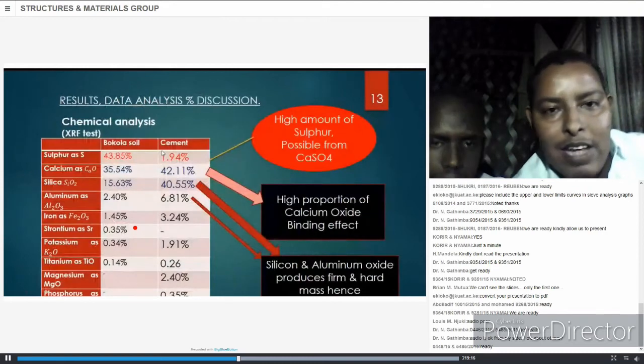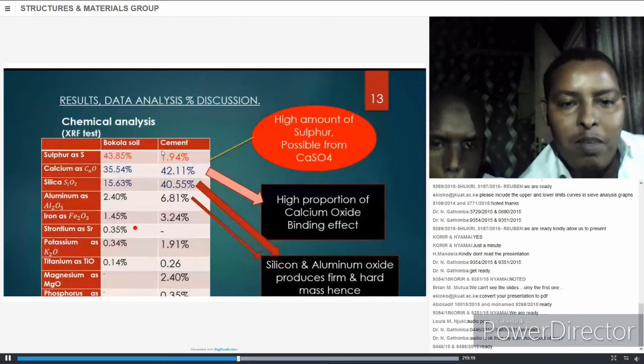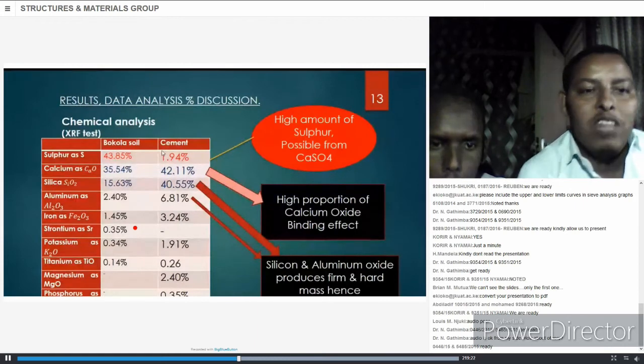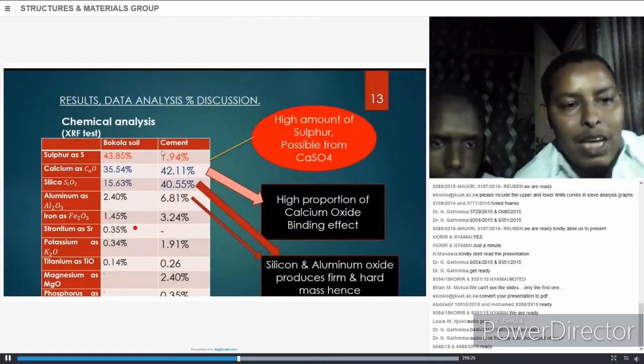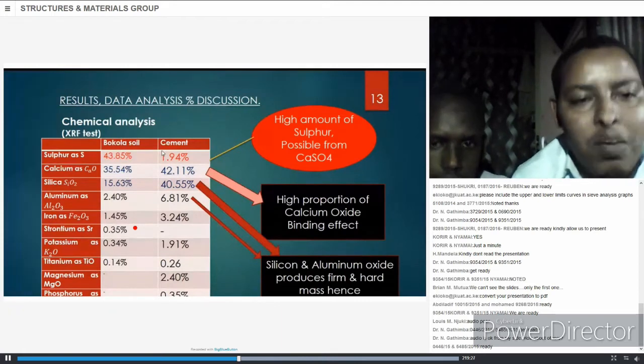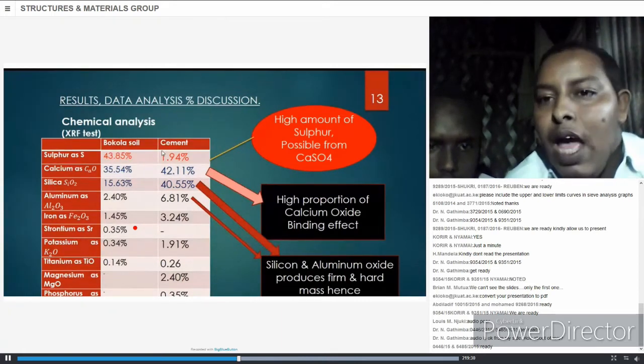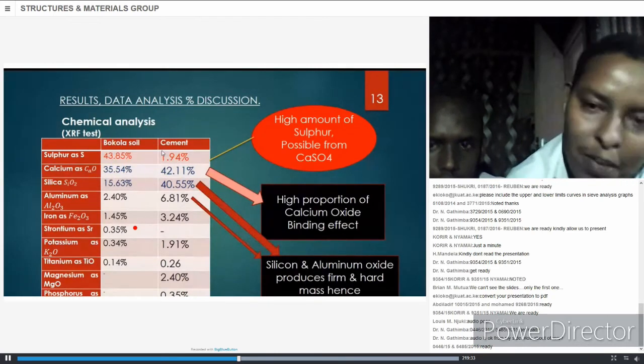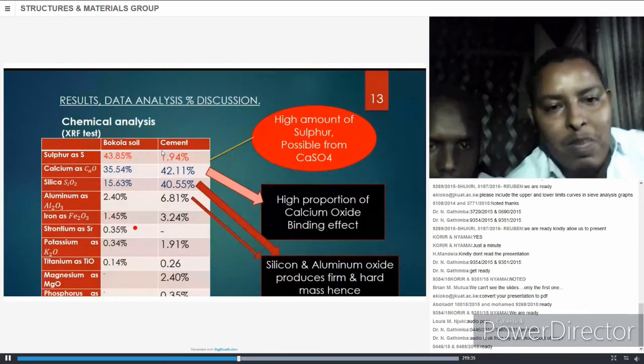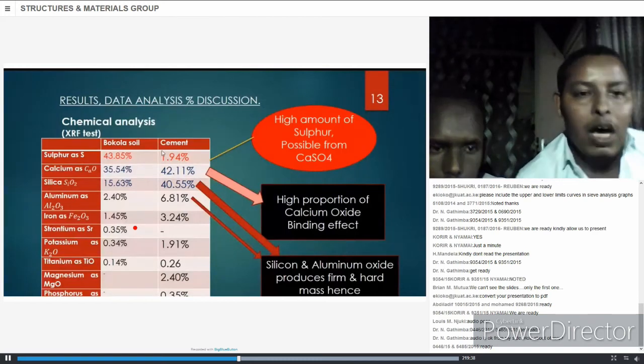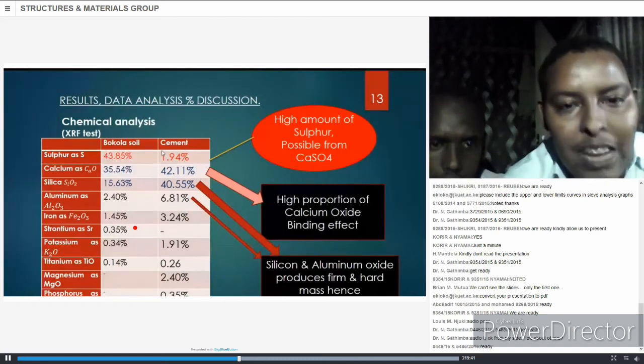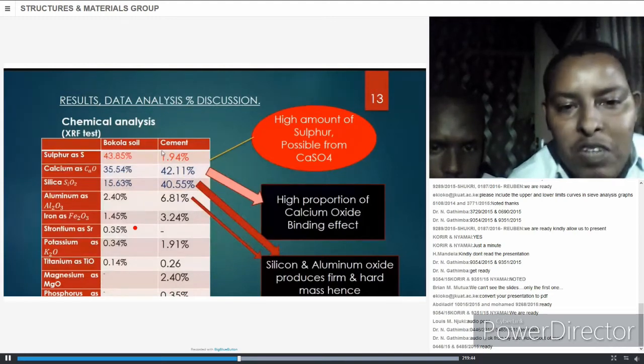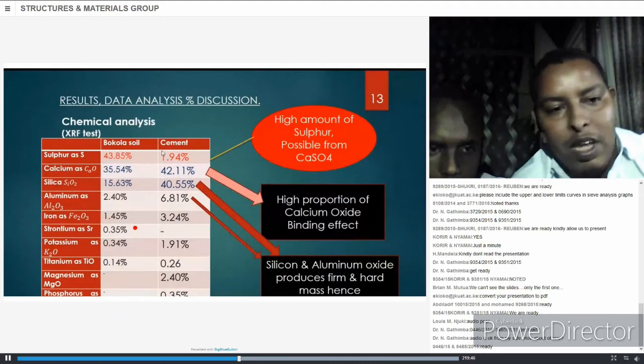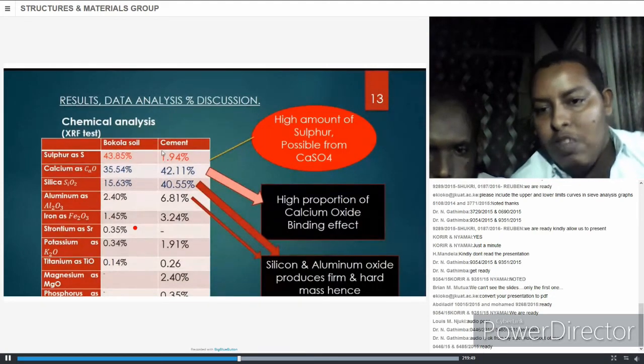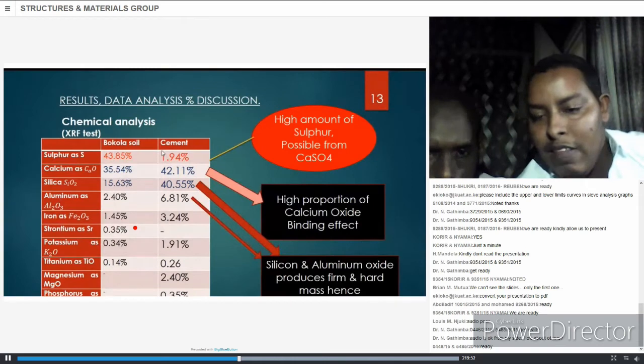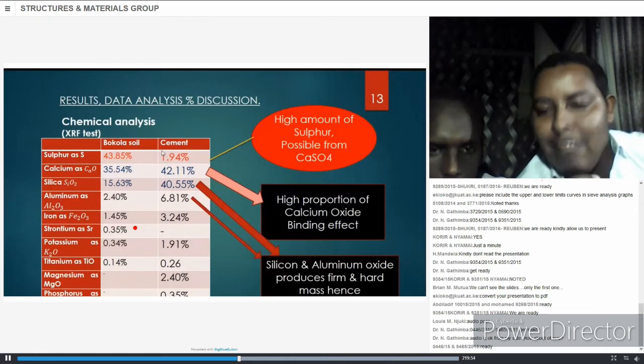Now, on to results, data analysis and discussion. The chemical composition of this bokola soil was analyzed using XRF test. We realized that it contained a very large amount of sulfur, 43.8%, against cement of 1.9%. This high amount of sulfur, unusual in cement, could be from calcium sulfate, making this material closer to gypsum than cement really. It contains a good amount of calcium oxide, 35 against cement 42, silica 15 against 40, and these two compounds are very important in cement because they bring the binding effect, and the silicon and aluminum produce a firm and hard mass, hence the strength development.